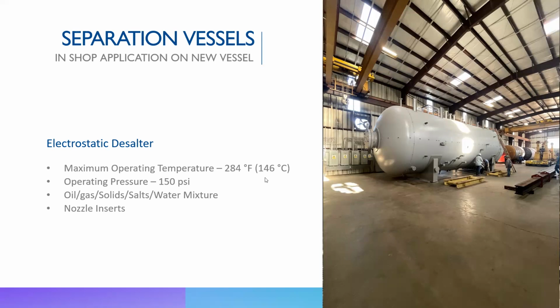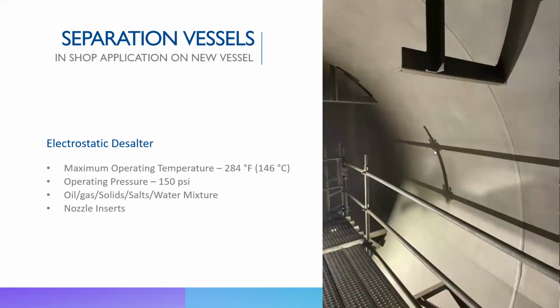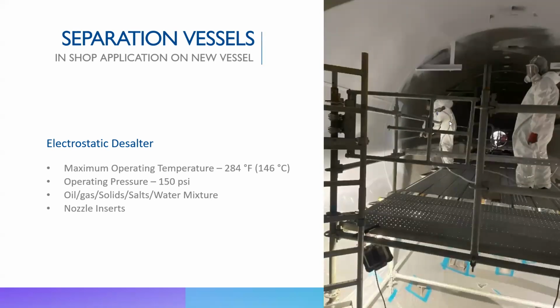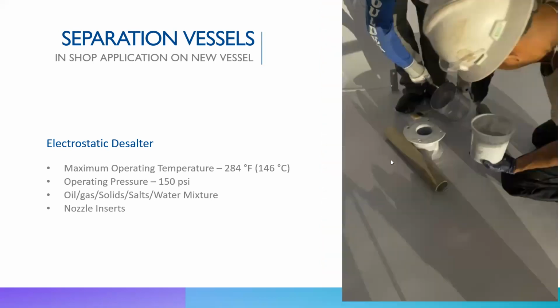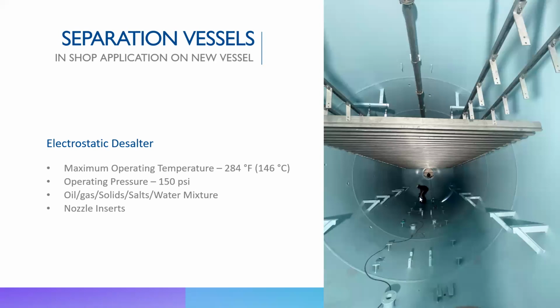This is just one application done last year. Had some good pictures, so I put it in here. This was operating at 284 degrees, 150 psi, and had an oil, gas, solid, salts, and water mixture. And as you can see, this is the full process. So we blasted the internals and applied a 2-coat spray applied liner. We also did nozzle inserts, which is a tube fabricated out of Belzona that's inserted into the nozzle and glued in with Belzona to have that coverage throughout the nozzles. And this is your finished product.